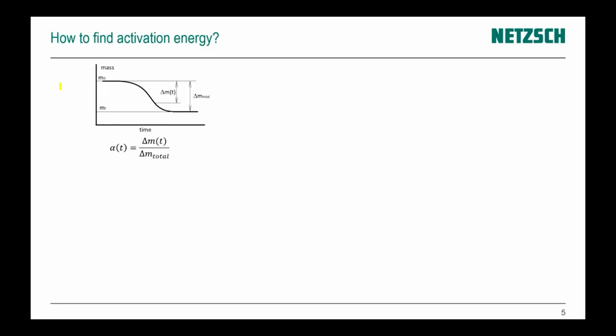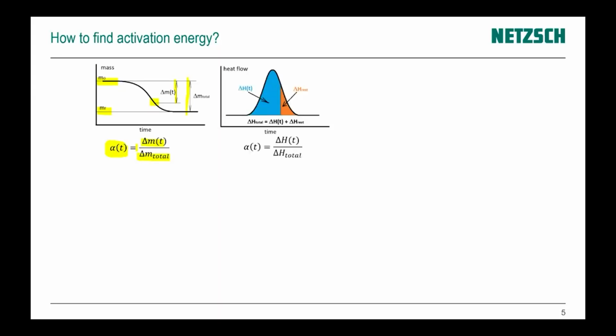The first question: how to find activation energy. For example, if we have TG and the mass of the material changes from initial mass to final mass, and we have a total mass loss and the current mass loss at the current point, then the ratio of the current mass loss to the total mass loss is the value of alpha, which is the conversion and changes from 0 to 1. If we speak about DSC, then at each point we have the partial peak area from the beginning to this point, and if we make a ratio to the total peak area, then we have alpha, which changes from 0 to 1 during our reaction. This is our degree of conversion, and it changes from 0 to 1, independent of the type of the data.